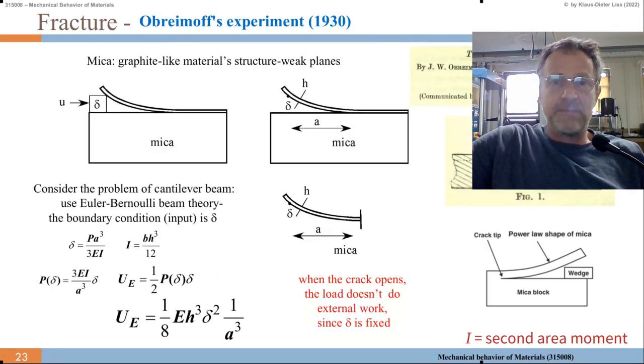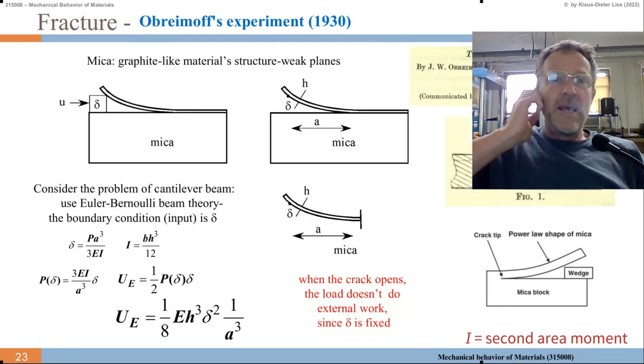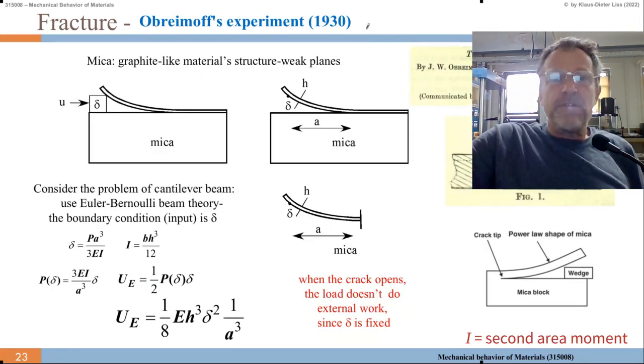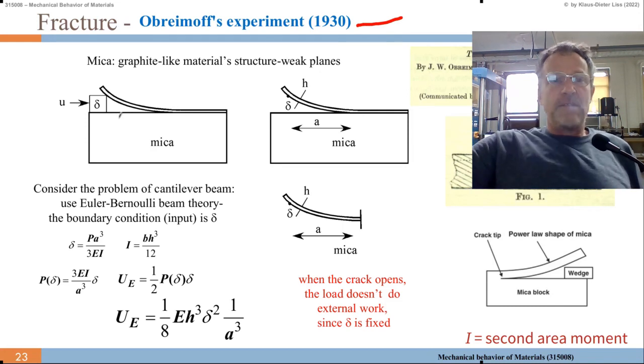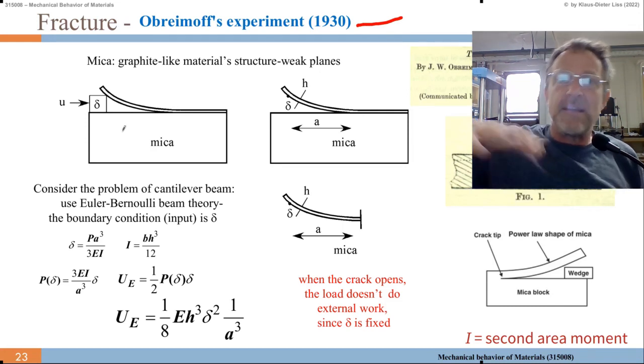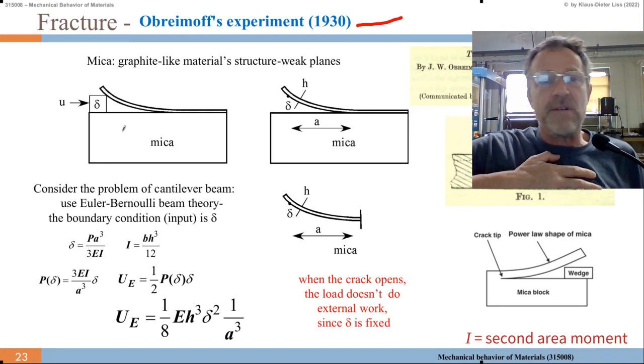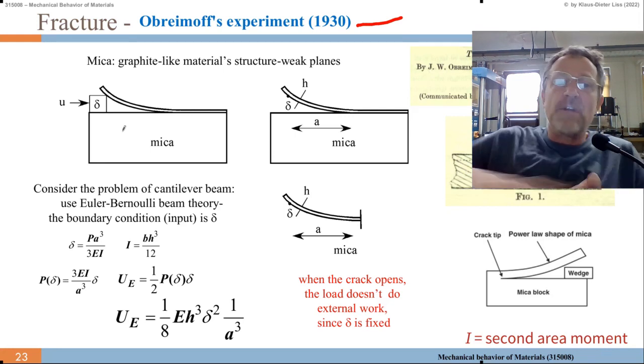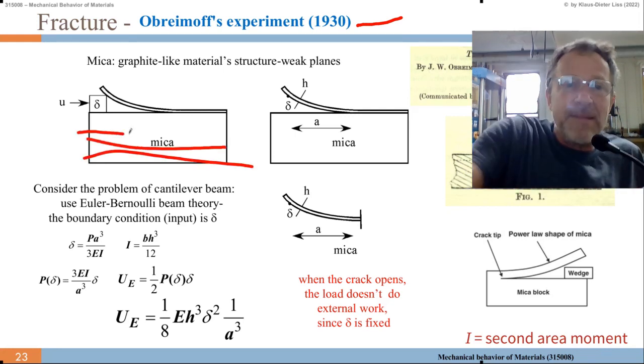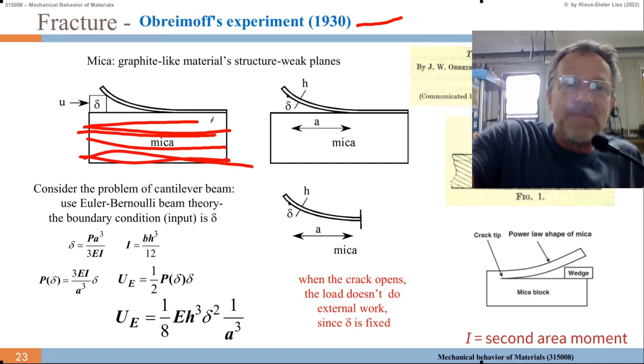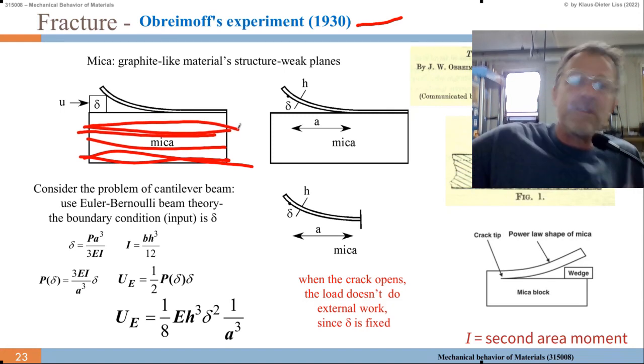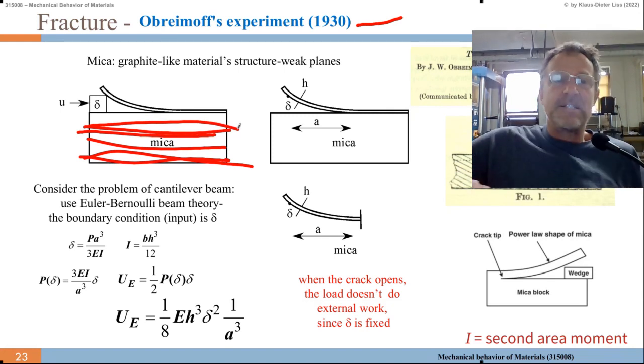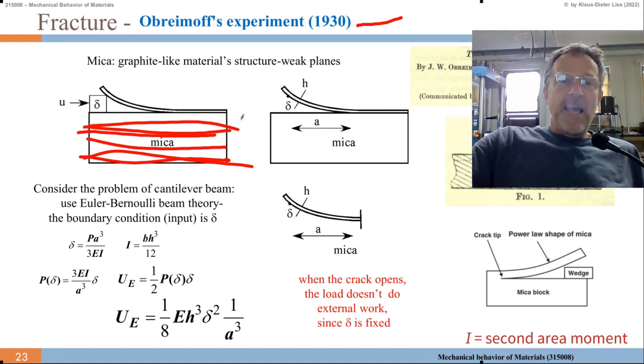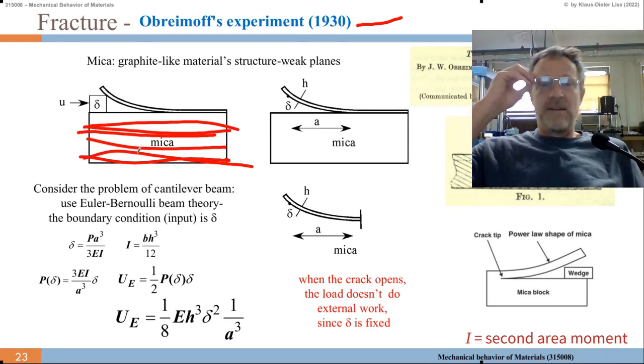Obreimov did this experiment in 1930. He took this crystal mica - mica is a bit like graphite, you may know it, and it cleaves off. So you have lattice planes, horizontal crystal lattice planes, a single crystal, and then you can cleave planes off. This is a so-called C-plane. It's a very anisotropic crystal.